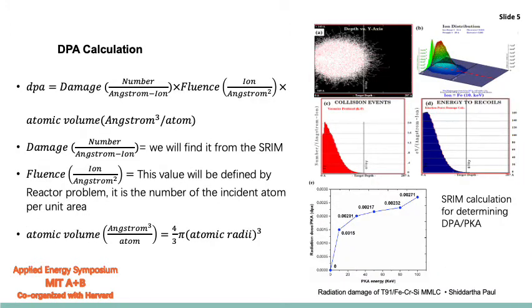We have used the SRIM calculation to determine the DPA per primary knock-on atom. What the primary knock-on atom does is displace the neighboring atoms, which results in an atomic displacement cascade. To evaluate the radiation damage, the DPA or the displacement per primary knock-on atom is a fundamental parameter that characterizes the lattice displacement events. For determining the DPA per primary knock-on atom, we have used the same structures and simulation settings in SRIM that we have used in our molecular dynamics simulation.